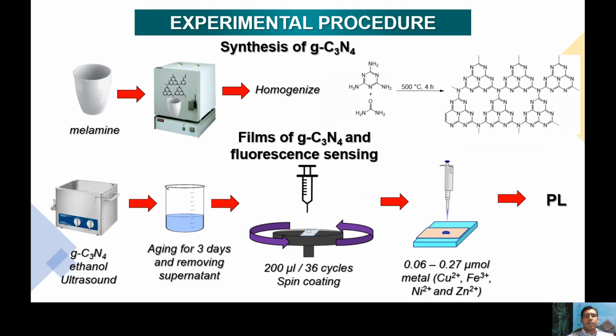First, we use melamine as precursor in order to get the C3N4, and we use the condition of 4 hours and 500 Celsius degrees. And then with the C3N4 material, we made films of this material by spin coating technique. We made a dispersion of the C3N4 in ethanol, and with the films, we did photoluminescence analysis for some metals like copper, iron, nickel, and zinc.